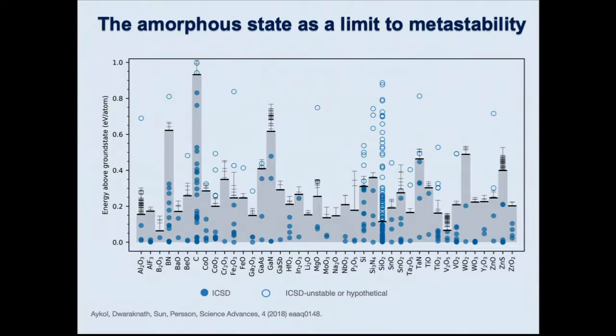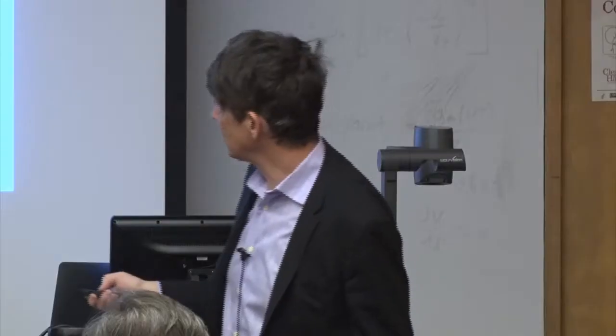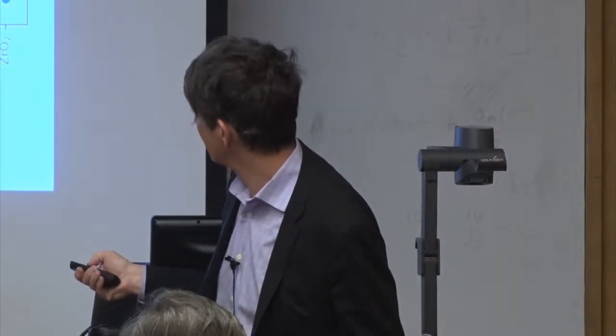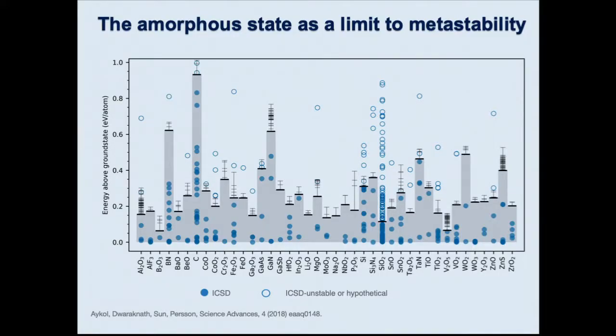And what's interesting is this criterion picks up chemistry. Look, giant metastability in carbon. This is a discussion we had yesterday. Carbon goes up to 800 millielectron volt per atom, and that's the buckyball, actually. But then there are other things like boron oxide, which has barely any metastability. Titanium oxide, vanadium oxide, have a lot of metastable compounds, but not a large energy range over which they live. Okay, so you think we solved the problem, because we have an energy range now for metastability, so maybe everything in this range can be made by a clever chemist. This clever chemist, which we don't know who he is, or she is.